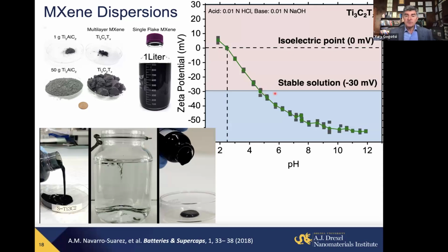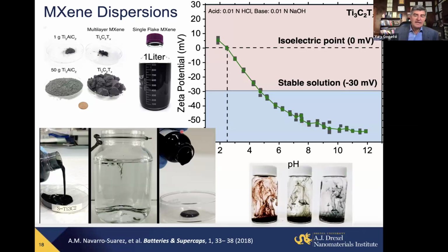And why is it possible without any additives? Because MXenes produced from an aqueous environment, having oxygen and OH on the surface, have high negative zeta potential. It means there is negative charge on the particles. There is repulsion in solution. You don't need to add surfactant, nothing. Just disperse in water, and you will form MXene paint.